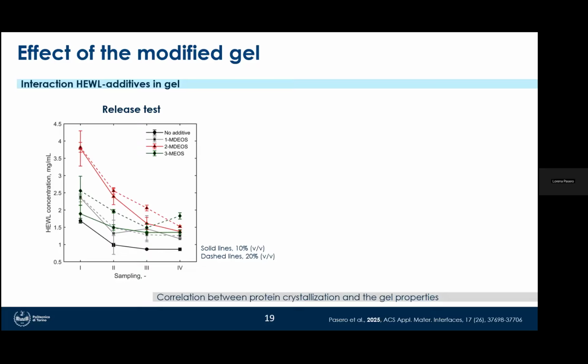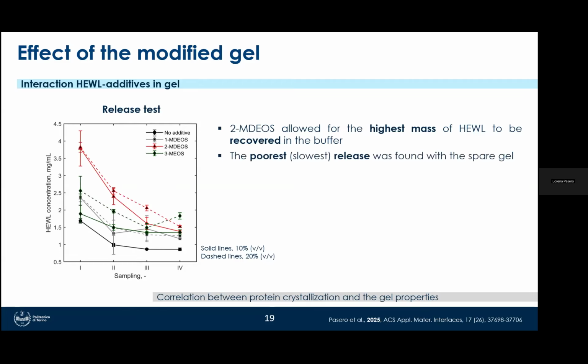Here in this graph, we can observe the release profiles in the presence of additives at 10%, the solid lines, and 20%, the dashed lines. And this was performed at different time points, from the first one, which was 24 hours, and then up to 140 hours. So here we could see that the highest recovery of lysozyme, and so the highest release of protein, was reached through the modification with the 2-methyl groups additives, while the slowest release, and so the highest retention of protein in the gel, was found with the bare gel, meaning that there was the higher absorption of protein in the gel.